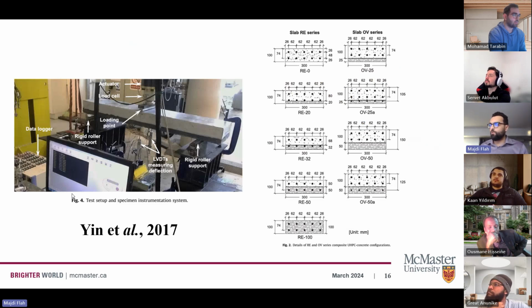The other study was in 2017, which is one of the few studies that focused on the behavior of the slab. So here there are two rehabilitation schemes. The first consisted of keeping the same thickness of the slab while damaging that area like we did in our experimental study, with different thicknesses, 20, 32, 50%, just to compare for UHPC. And for the overlay series, we're going to keep the 100 and put different layers of UHPC, and we're also going to study the behavior of putting reinforcement inside the UHPC layer.